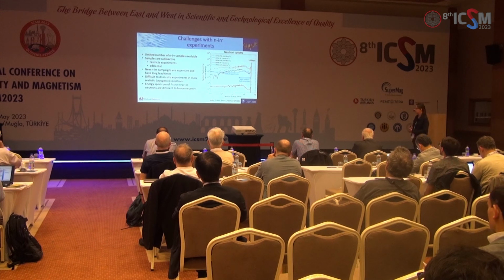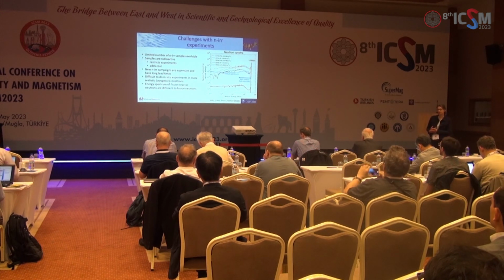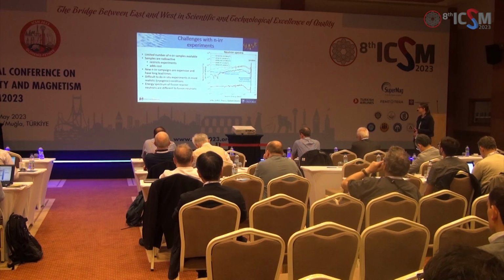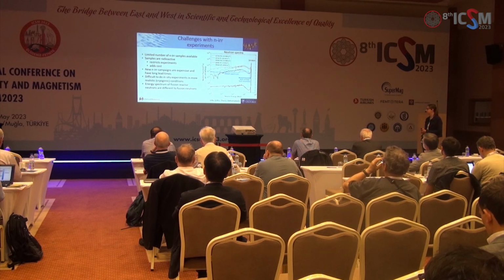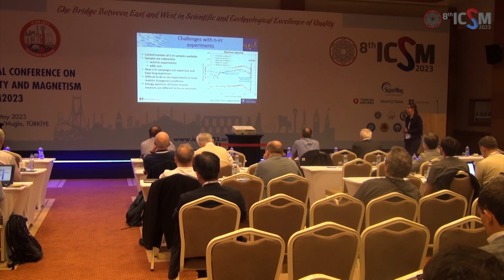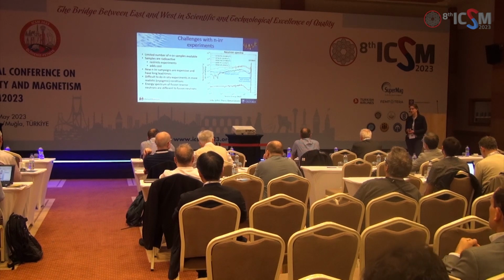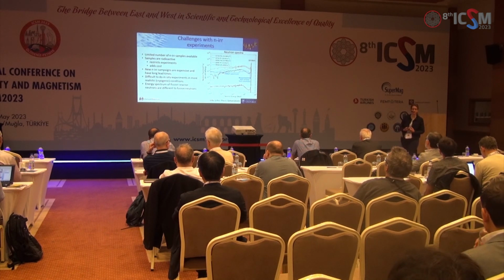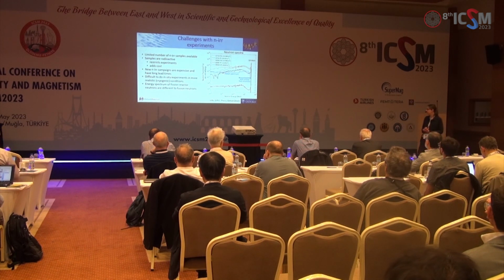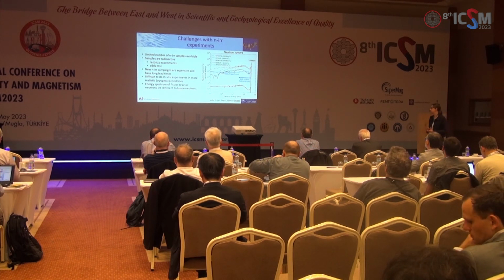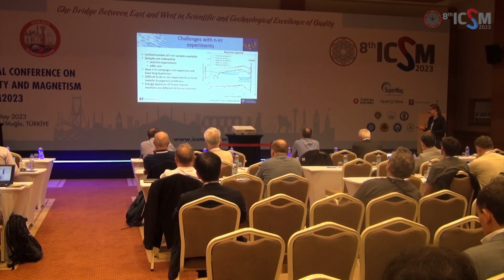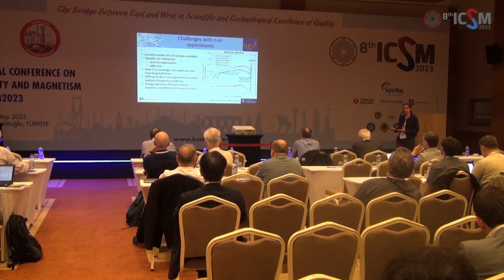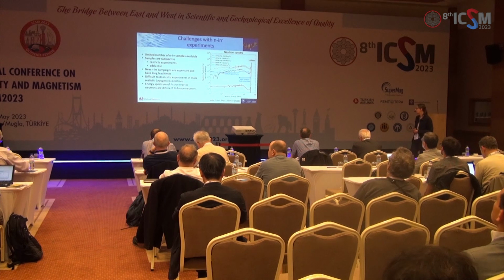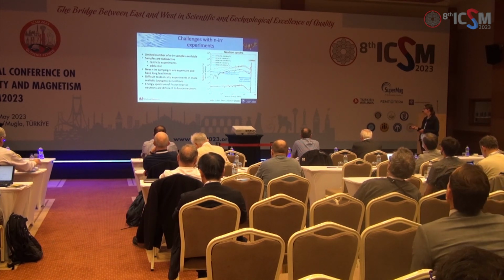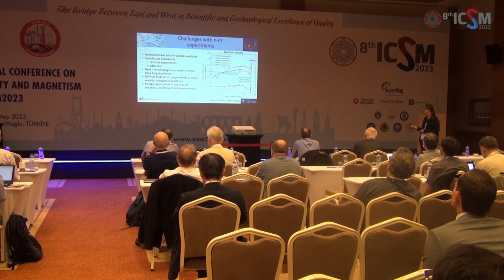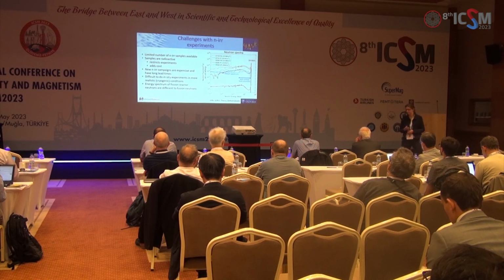So what are the challenges with these neutron irradiation experiments? You'll see that a lot of the experiments I showed you came out of one set of irradiations done in Vienna. There are not very many neutron irradiated coated conductor samples available to look at. The samples are radioactive once they've been neutron irradiated. The campaigns are expensive and take a long time. When you've irradiated your samples, you then have to wait before you can do lots of the testing on them because they're too radioactive. It's quite difficult to do things like in situ measurements in those kinds of reactors. And of course, a minor point really, but an important one too, is that the energy spectrum for fission reaction neutrons isn't the same as for fusion reaction neutrons anyway. The fusion spectrum has a peak here at 14 MeV, whereas the fission spectrum is fairly flat and has maybe a little bit more of these fast neutrons, but not very many of these high energies of 14 MeV.